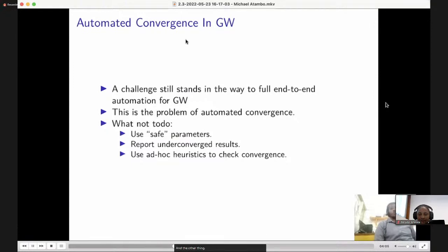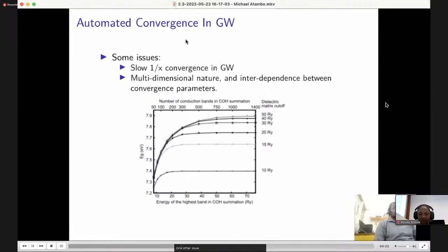The other thing that should not be done is to report under-converged results. However, ad hoc heuristics have been applied. However, since these are not very systematic, they are not very broadly applicable. One other issue also needs to be considered when thinking about the idea of automated convergence. So this is a problem of slow convergence in GW. It is known to present a characteristic convergence rate of about 1/x. So this can be a problem because if it's converging really slowly, it becomes somewhat tricky to reason about whether a calculation is converged or not. And the fact that there are multiple such parameters in GW makes it a non-trivial multi-dimensional problem.